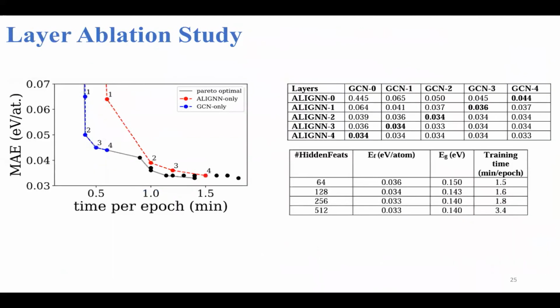Okay, so layer ablation study. Any deep learning should have this component. So we want to know the ALIGNN and GCN layer. We saw that if you use at least 2 GCN and 2 ALIGNN layers, we get reasonable performance. This is the JARVIS-DFT formation energy ablation study. And similarly, we use around 200 hidden features. Then we get reasonable models. And we did several ablation studies for other components of the ALIGNN model as well, which is available in our paper, but you can look into it if you're interested.